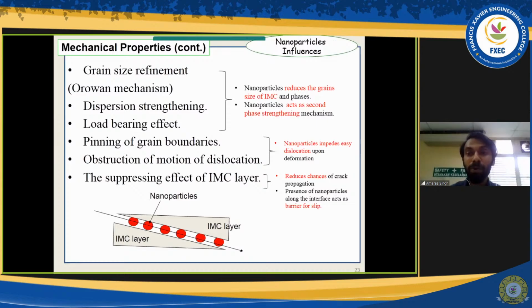So when more and more dislocations go around, there are piled up dislocations, so it's harder for the stress to penetrate. And the last one is the suppressing effect of the IMC layer, which is what I explained earlier. It will block the diffusion process between the elements in the solder and the substrate. Therefore, we can get a thin IMC layer.